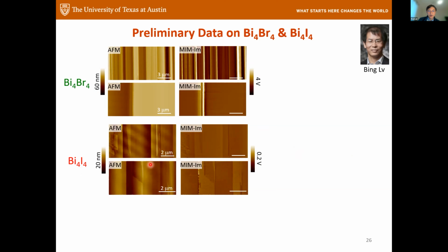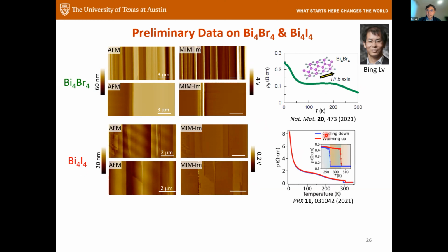Okay? And so I must say this is really preliminary. So we got a sample around Thanksgiving, and these were taken during the winter break, and we didn't even have time to fully analyze them. But after listening to many great talks in the past 2 days, I think at least this is telling us something. It's telling us that maybe this indeed is quite different. So most likely, for example, this is maybe in the alpha phase, but we need to heat it up and see whether we can access the slightly higher temperature and sort of get these bright lines in the iodine sample.